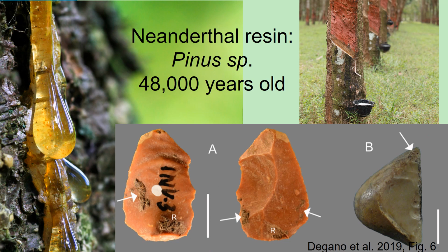There are a number of Neanderthal tools with residues like the one that you see here. So here you see these residues attached to the stone surface, and these residues were tested with gas chromatography, mass spectrometry, and they were found to be pine resins. They may have been mixed with beeswax, but this evidence is very speculative. These adhesives were used to haft the stone tools, and we know that from the location on the tools. The sharp working edges are free, and it's the blunt sides suited to hold the haft that show traces of resin.